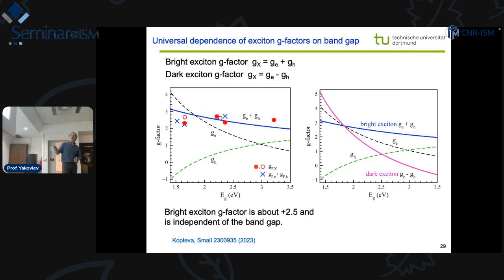For the dark exciton, the situation is different. It's not nearly constant, it changes very strongly. For the dark exciton, which is the difference of the electron and hole g factors, the dependence is strong. And this strong difference between the bright and dark exciton g factors gives a good playground for spin physics, because you can go into one range where one is larger than the other, or equal to each other, or they go in opposite directions.